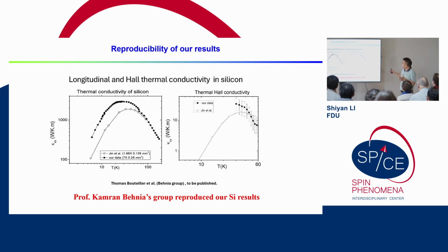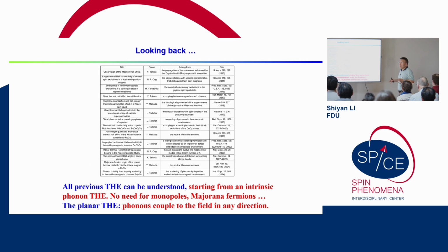Basically now we did a lot of checks, and some other groups reproduced our results. So that means we now really have the universal phonon thermal Hall in all single crystals. Although it's very striking, if you look back at all these measurements, everything seems reasonable now. So all previous thermal Hall effects can be understood, starting from the intrinsic phonon thermal Hall. So no need for exotic monopoles or Majorana fermions, and I'm not sure if we need magnons, right?